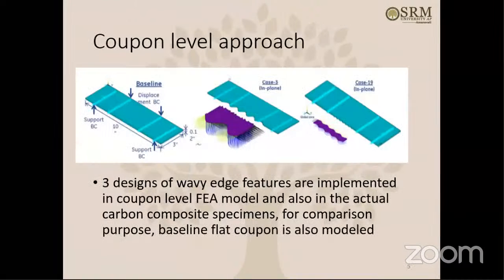So we'll see. Okay, as you can see, we used finite element analysis to create these simplistic coupons, which can be tested in the lab, just 10-inch long and 3-inch wide. The left-hand side figure is the baseline coupon, which is straight. There are no wavy shapes there. In the other cases, the wavy features are implemented on one of the edges of the coupon, just to find out the effect of that wavy feature.